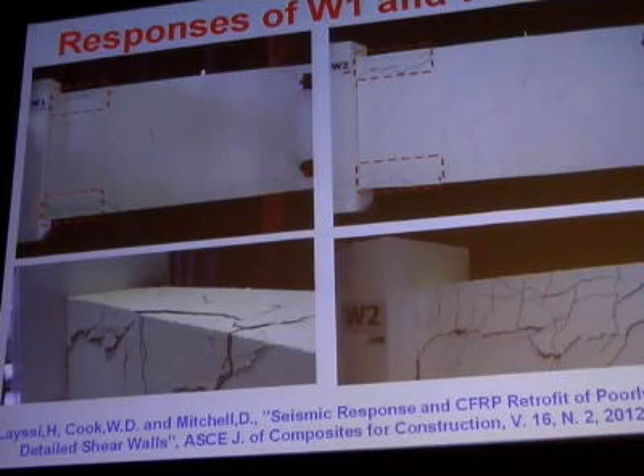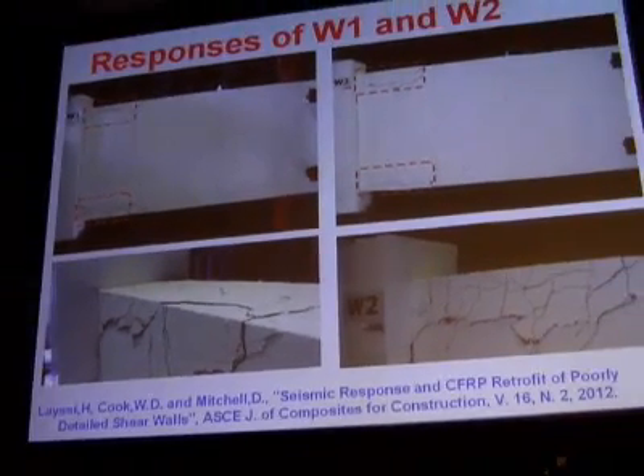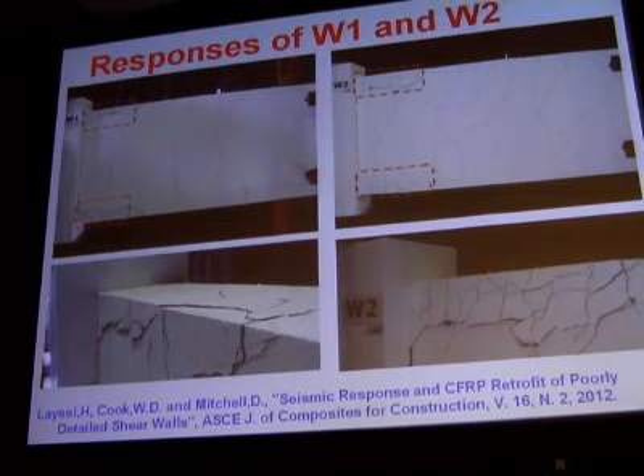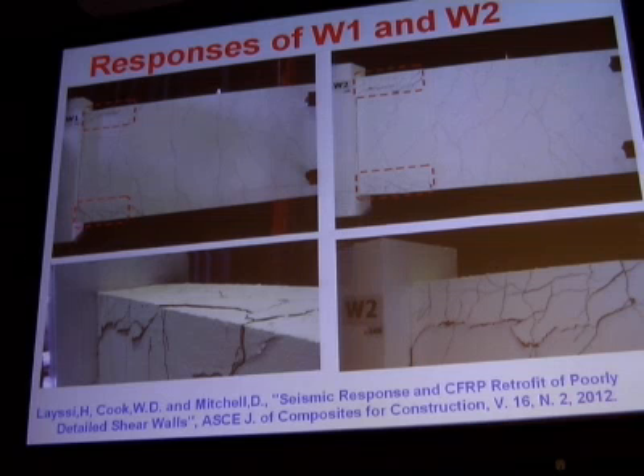The way in which these 2 walls failed, W1 with the 2 20Ms, had failure of the lap splices at the base of the wall, as you would expect. The W2 test with the 4 20Ms in the critical section has the lap splice splitting failure in between the 2 levels of 20M bars. You can see the close-ups in the bottom of the figure showing that these failure planes took place in slightly different locations because of the difference in the flexural reinforcement.